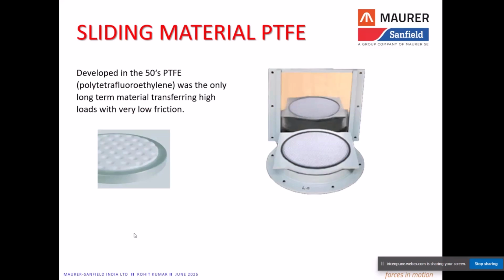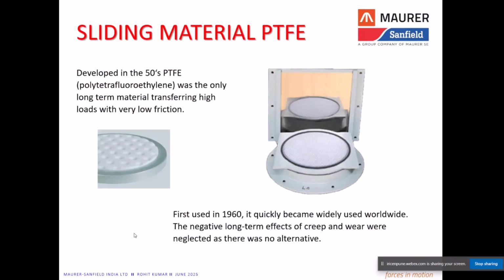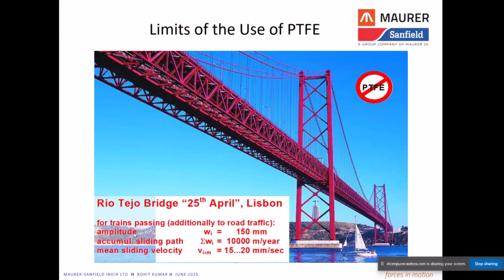Now, the materials used inside the spherical bearings are normally only two. One is steel, which gives you a higher service life, and the second is the thermoplastic material. The thermoplastic material used inside the bearing is PTFE, which was developed in the 50s, and it is the only material providing higher loads and very low friction between the materials. But now there are some cases where this material is not fulfilling the requirements of the structure.